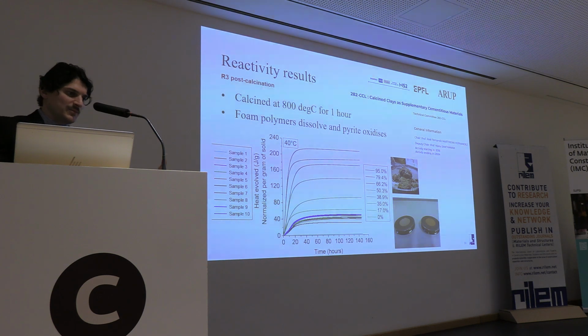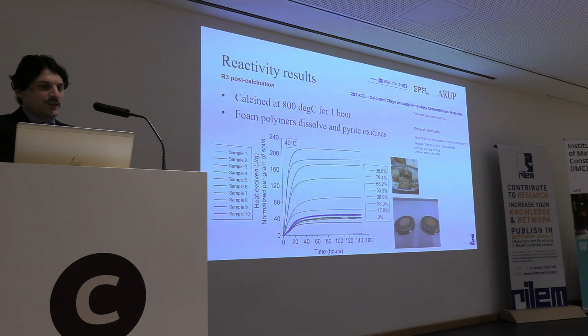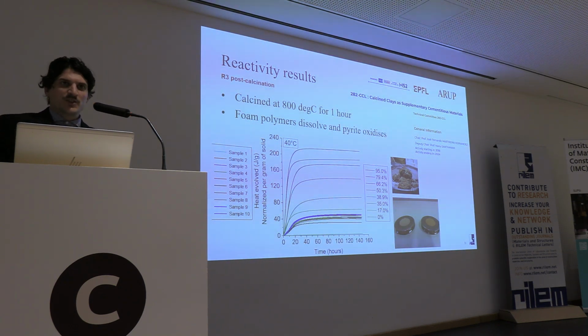And at the time, we were privileged enough to talk with Karen, and Karen was even invited to come over to our headquarters in London, and we talked about the potential of using this clay as a supplementary cementitious material in terms of calcined clay. This was the start of it essentially, because we gained confidence in the potential performance of the material. So we carried out some initial tests at EPFL. You can see this R3 testing here. We're on the low side of kaolinite content, really 17-20%, which is not great, right?